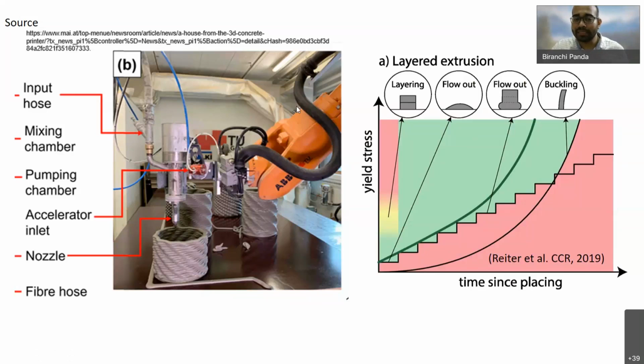And this complete thing has been depicted in the picture: with time, if you want to print a higher or tall structure, the yield stress has to go exponentially high. And this can be possible, as I mentioned, by adding the chemical or by adding some microwave heating, which can cure the concrete at a much faster rate.